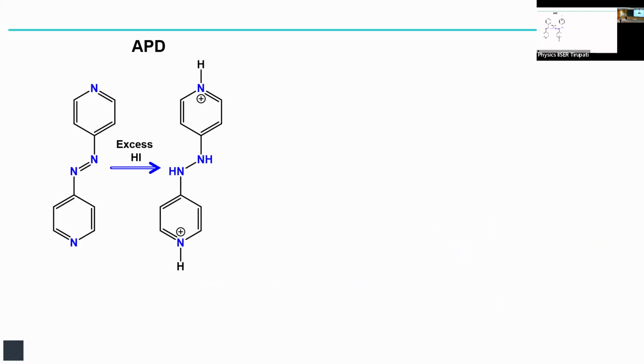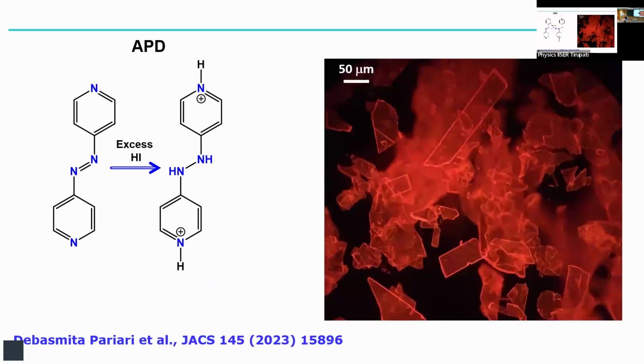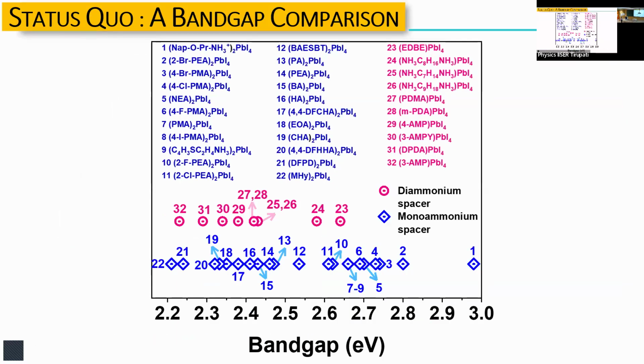This is the molecule she used. This molecule is too large for the cube, that body center position. So it splits open the cube into a two-dimensional object. Beautiful crystals you can make. But the result, when she took the material and looked at the band gap, here are all the band gaps of such two-dimensional halide materials, with two different color codings. Do not worry about that because there are two different ways this can be done. But the band gaps are given here. You can see the lowest band gap is about 2.2 something. The material that Debashmita made has a band gap here, which you can see is the smallest band gap. Even today, it holds the position of being the smallest band gap material in this class of compounds.